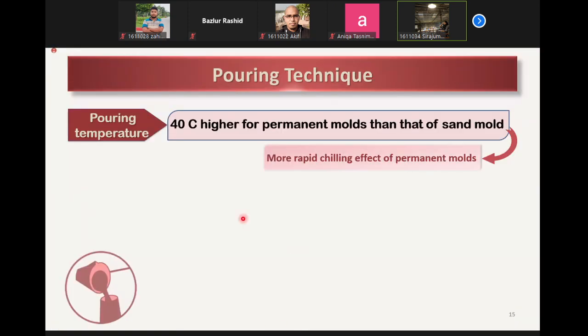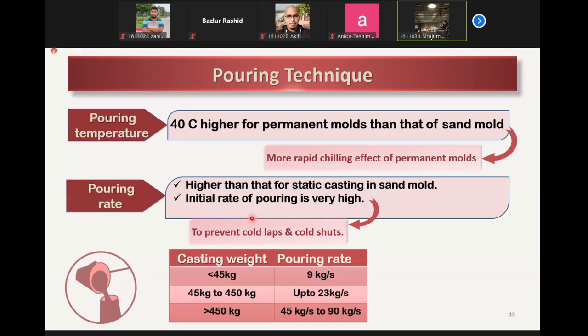Generally, in permanent molds, pouring temperature of molten metal is 40 degrees Celsius higher than that in sand mold. This is because of rapid chilling effect of permanent mold, and for the same reason, pouring rate, especially the rate at the beginning, must be very high compared to the sand molds. Otherwise, cold laps and cold shuts may occur. In this table, we can see the pouring rate requirement for different ranges of casting weight in this process.